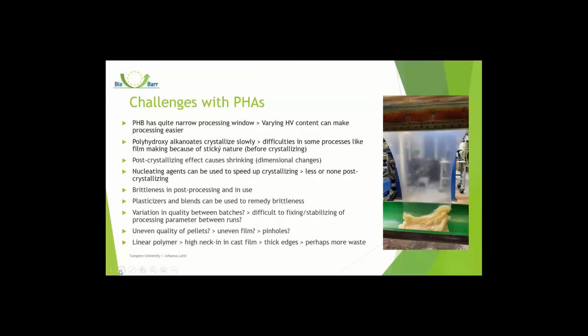So they typically crystallize very slowly, and this can cause, for example, sticking problems on the chill roll when producing film through the casting process. Also, this crystallizing can affect the end-use properties of the film, for example, some shrinking effect. We can affect this behavior by using nucleating agents, and this can be used beneficially to affect this process of crystallizing.